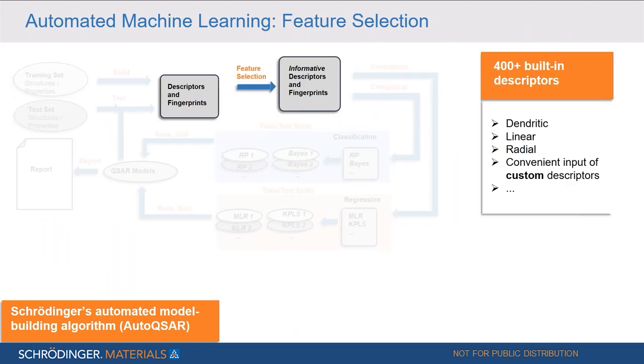We can now also look at the automated steps individually. The first step in this procedure would be the generation of descriptors and fingerprints. And AutoQSAR has many built-in descriptors like dendritic, linear, or radial fingerprints, but also the flexibility to select custom descriptors. The next step would be the feature selection step, where the descriptors and fingerprints that do not provide a statistically significant amount of information are discarded. And the remaining ones are then filtered again to remove redundancy. This means after the second step, we end up with informative fingerprints and descriptors.